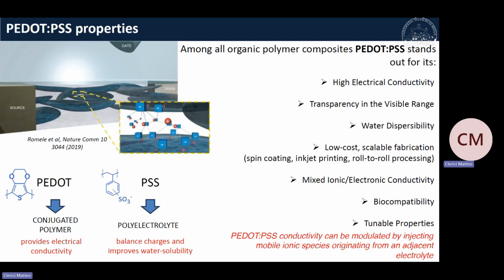We want to make, for example, an optical interconnection, so we need that to be transparent in a pretty broad range. But most importantly, we understood that we could modulate the refractive index properties, well, the conductivity to start with, and then the refractive index as a consequence, by injecting some ionic species from an adjacent electrolyte that stands close to PEDOT. So if you take a look at how it looks, it's like a matrix. It's our PEDOT and the PSS on those big chains laying inside the PEDOT. So it's a kind of mixed material.